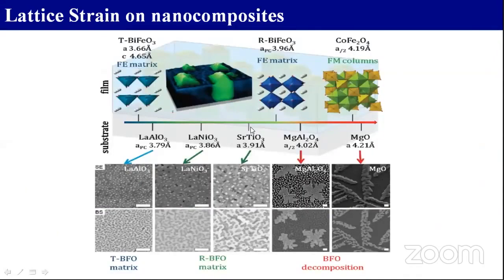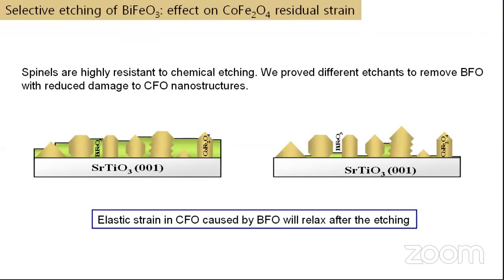If you have strontium titanate, you can clearly see the rhombohedral perovskite matrix. Then if you have a more compressive stress, that changes to a tetragonal structure. But if you have a tensile stress, growing an epitaxial film is very difficult because of the huge tensile stress. The bismuth ferrite decomposes and grows in a dendritic growth manner. So we wanted to measure the strain directly.